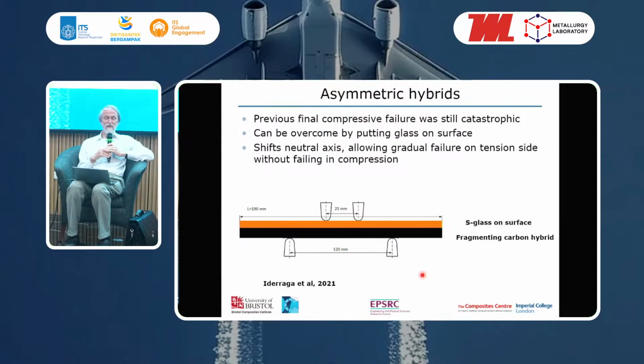So the previous results still showed us a catastrophic failure. So we got fragmentation, but still both the layups I showed finally failed with a catastrophic failure in compression. So we wanted to see how we could overcome that, and one of the ideas was to make a hybrid where we had glass on the compression and a fragmenting carbon hybrid on the tension side. So the idea here was to stop the compressive failure and activate the gradual failure in the carbon and see whether we could overcome this catastrophic failure. So by doing this, when the carbon starts to fragment, we get a shift in the neutral axis, and this allows gradual failure on the tension side without failing the specimen in compression.